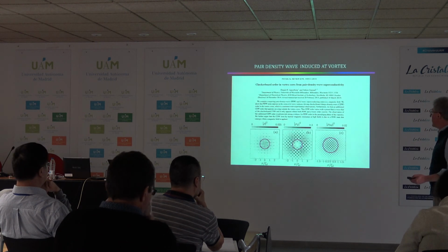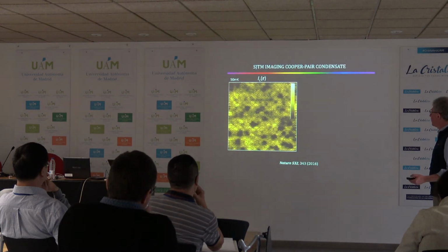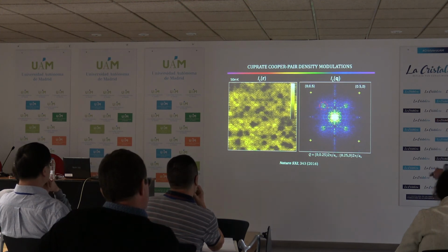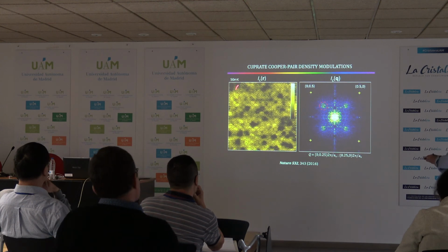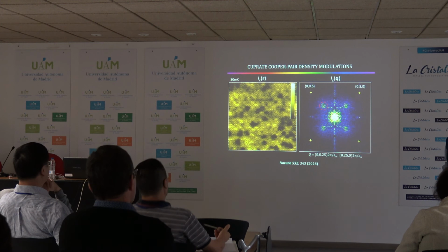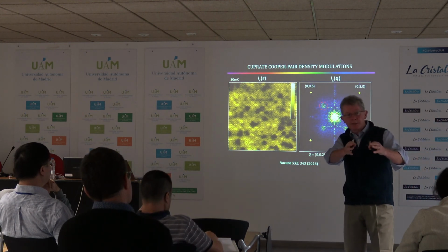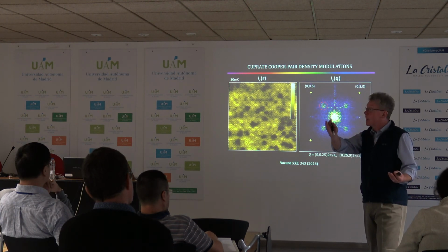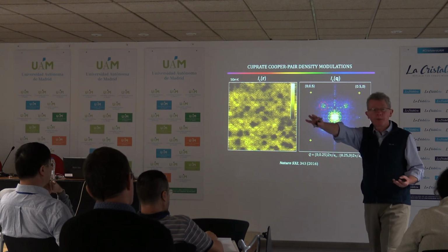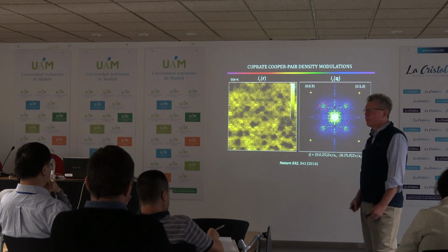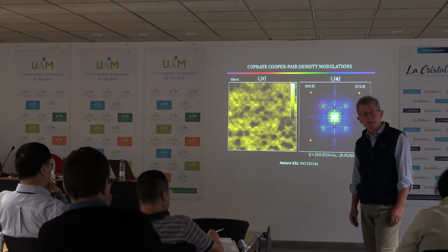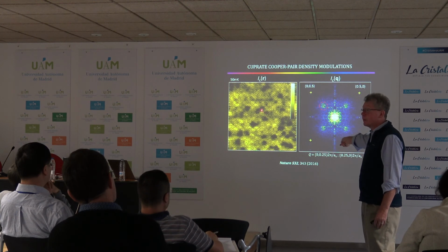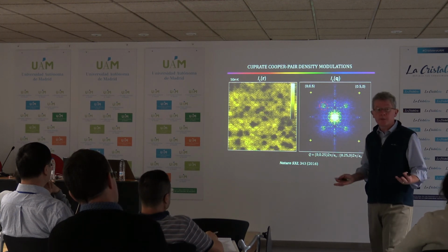That's obviously a key question, but let me re-emphasize the answer that I just gave to Mohit, in a related way, in an attempt to answer your question. Forget these zinc things. Let's look at a region where there isn't a whole bunch of defects. Now we're looking at the condensate. We don't have to hypothesize what the properties of the condensate are. We can see it. It's got a modulation on it, but that modulation is less than 10%. So there's a homogeneous background superfluid with a weak modulation sitting on it. There's a lot of heterogeneity if you put the right impurity atoms on the copper side, but otherwise, we think this stuff is homogeneous.